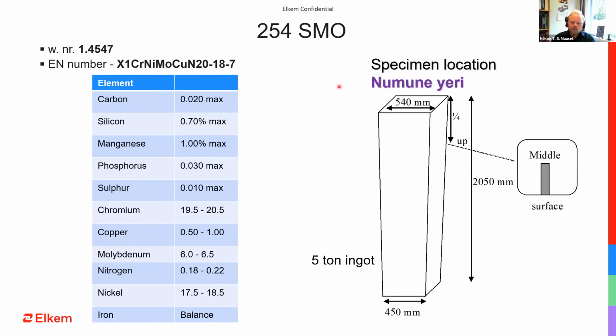This first case here is not from a foundry. This is from a steel mill producing ingots. This is the steel grade called 254 SMO. You see, it's a very highly alloyed super austenitic steel. The 20% chromium, less than 1% copper, 6% molybdenum, and then around 18% nickel. Also, you see a lot of nitrogen. So it's a really highly alloyed steel, and usually segregates a lot during solidification.